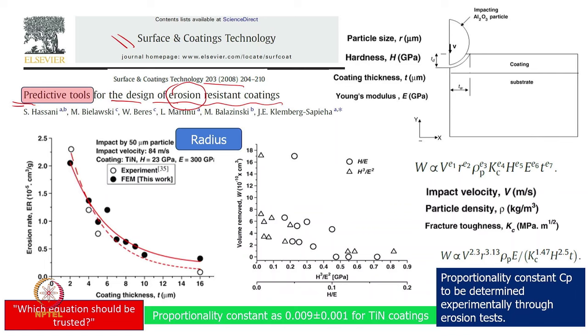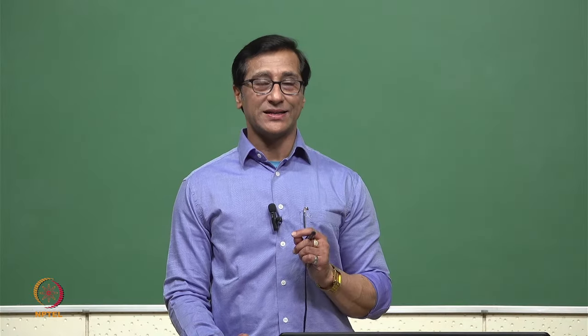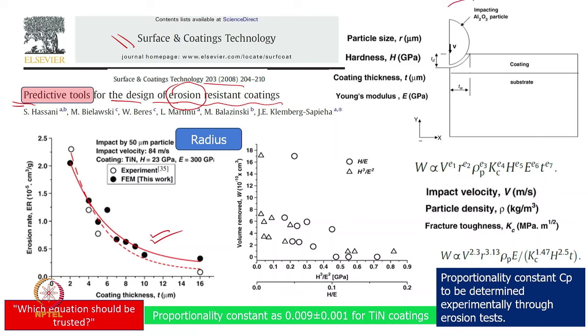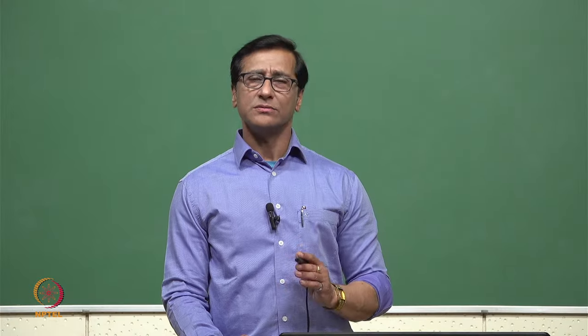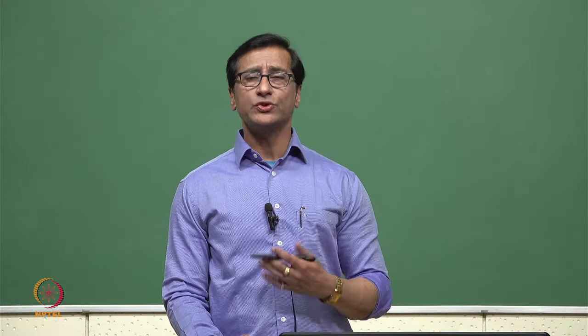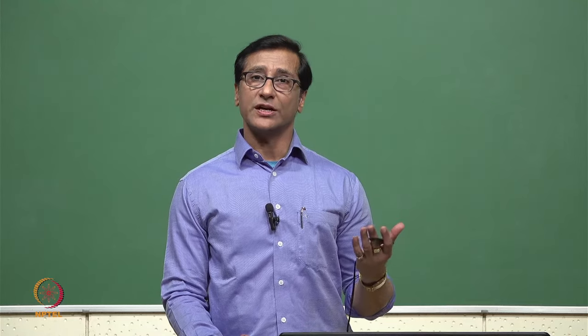What they have shown very clearly is that as coating thickness increases, erosion resistance increases, which in most coatings is the reverse. Many times we say that as coating thickness decreases, its wear resistance will increase. The question comes, why? This is because in erosion there is a third body particle. If the third body particle diameter or radius is on the higher side, naturally it will completely scrape the coating itself. So that's why they have used a word like thicker coating. And there is a trend now: depending on the situation, we can choose thinner coating or thicker coating, depending on the kind of application.